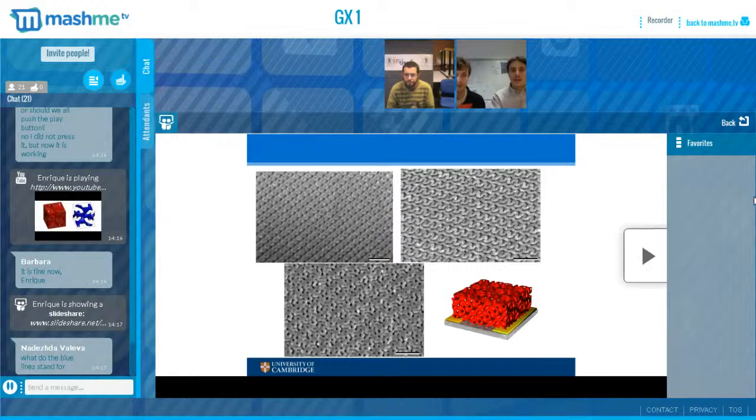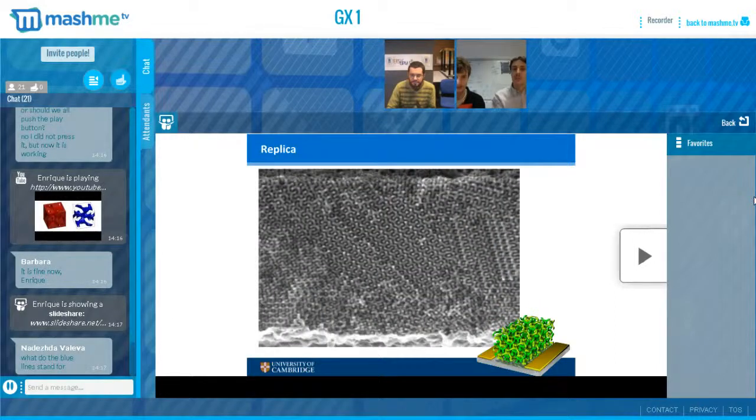So, as we said, this is the red structure after removing the blue polymer block. The next step is we replicate this structure with functional materials. In this image, you see nickel or nickel oxide. So we can prepare a lot of different materials with this nanostructure. And as you can imagine, the surface area is extremely high, so this material is highly active. In the middle, you can see this double wave pattern, which shows how periodic this structure actually is. This is after replicating the template and then removing the template, and then we make the SEM images. The point of the replication is that we can use the same template, using exactly the same polymers, and we just deposit different materials within it.